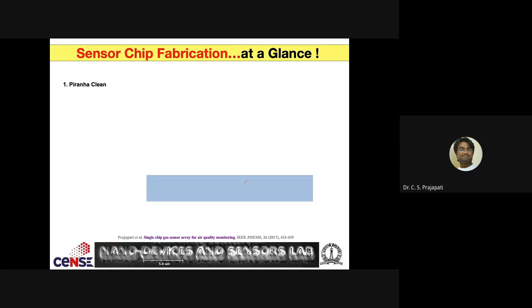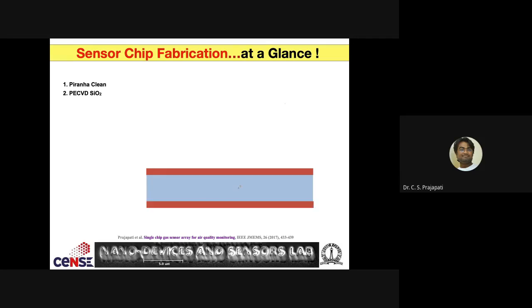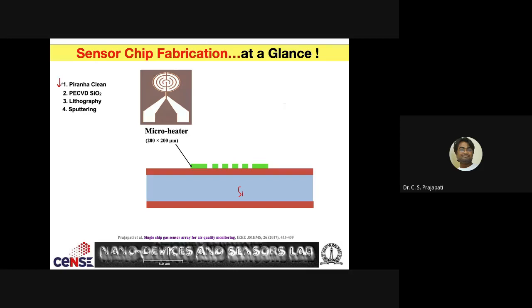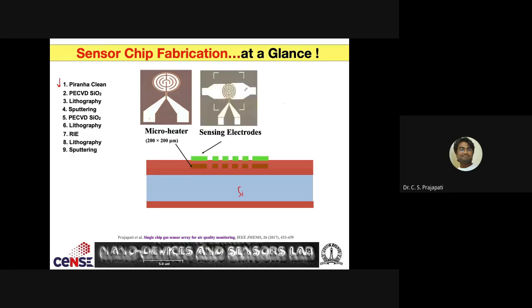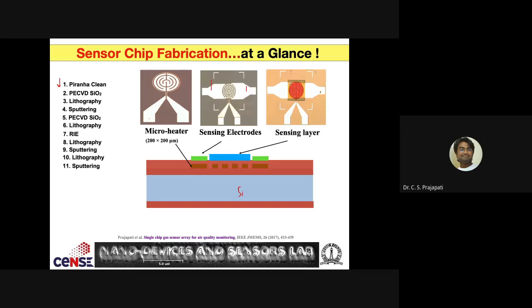Right. So how we fabricated this gas sensor chip, let us see quickly. We take the silicon, here. Then we passivate it with PECVD oxide. Here I have listed the process and tool. Then you pattern this micro heater, a Ti/Pt micro heater, on top of this passivated silicon. Then we passivate this micro heater with SiO2. Then we do RIE, basically to open the pads for the electrical connections. Then we put the sensing electrodes, which measure the resistance of the sensing layer sitting here. This is the fabrication process that we do.